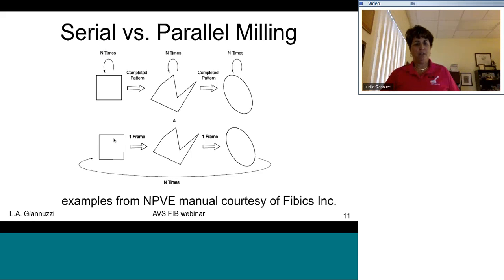In parallel milling, I'm going to do one entire frame of this first pattern, then jump and do one entire frame of the second pattern, and then jump and do one entire frame of the third pattern, and I'm going to do it n number of times, okay? So in parallel milling also, the number of passes of all of these has to be the same. Whereas if you do these three patterns independently, the number of passes can be independent, because you're doing one completion, and the second one, and the third one.